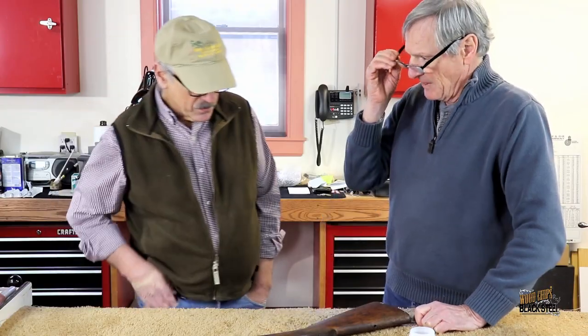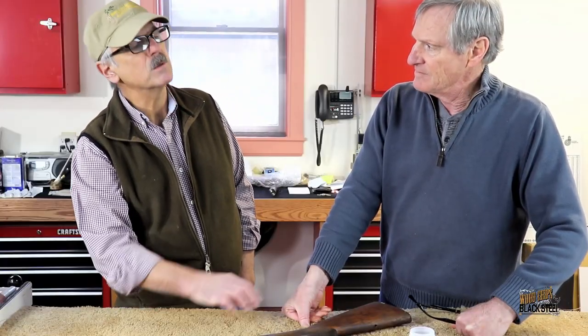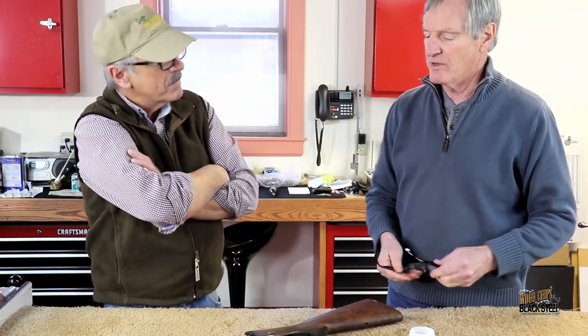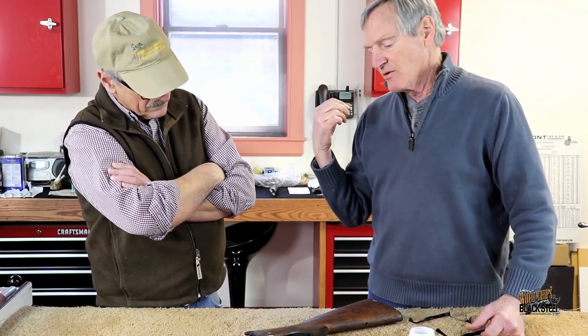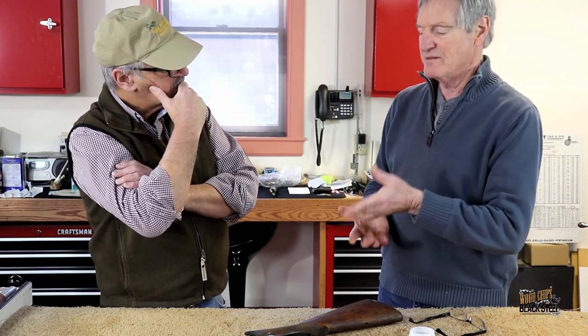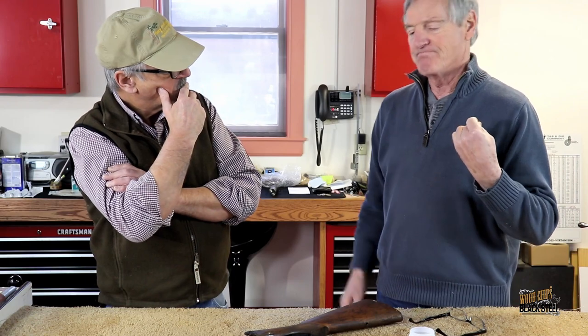Let's say I'm happy with this and I'm ready to get my epoxy in there. From the last application in a crack like this, how long would it be reasonable to wait before doing the epoxy job? I waited a week on this repair. Oh, you don't need to — not that long. I would do it within a couple hours. In an oily wood, that oil is going to come back into what you cleaned. I want to keep it as clean as possible, and acetone is a very rapid evaporator. When it's clean and ready to go, I would say a couple of hours.